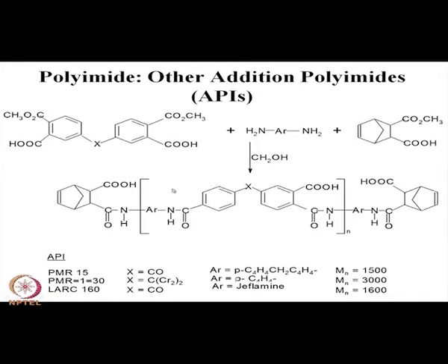So, that can also form the imide ring. This similar carboxyl group will be there at this position. So, this will form one imide ring, this will form another imide ring, and these reactive N groups are there as before. It will be cross linkable as well as polyimide structure will be formed, and at the same time this flexible linkage is there.